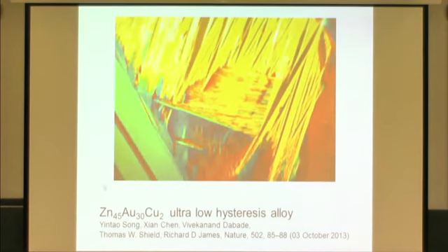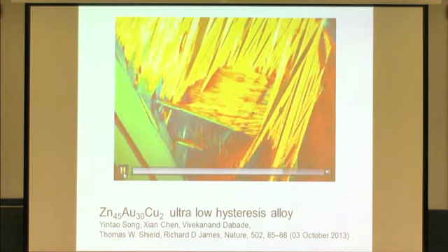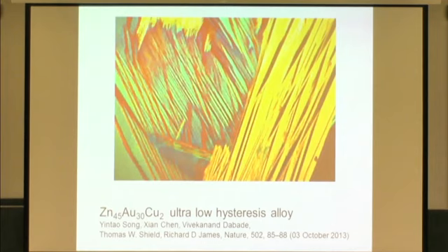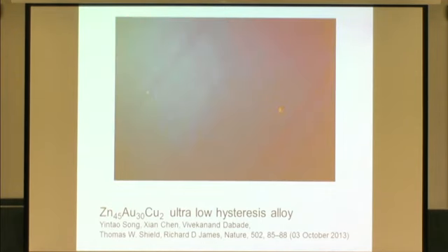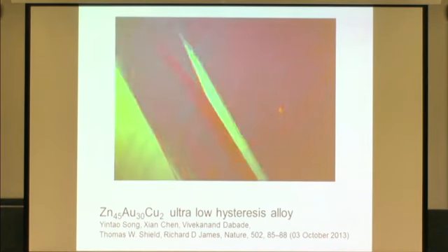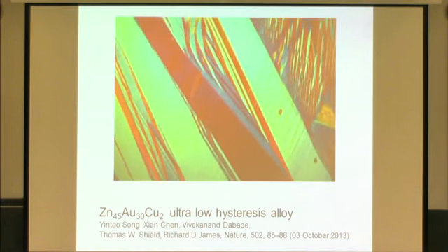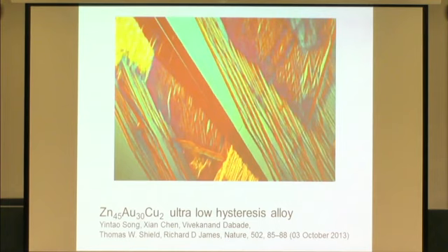And what's more, when you cycle them across the critical temperature, amazing things happen that you just don't see in any other material. You get completely different microstructures forming on each cycle, okay? And we have no idea why this happens. Indeed, you would expect, I mean, it doesn't have to make any interface at all, but it chooses to make these very complicated patterns. Perhaps resulting from that it's a polycrystal, but so far experiments haven't been done in the single crystal case.